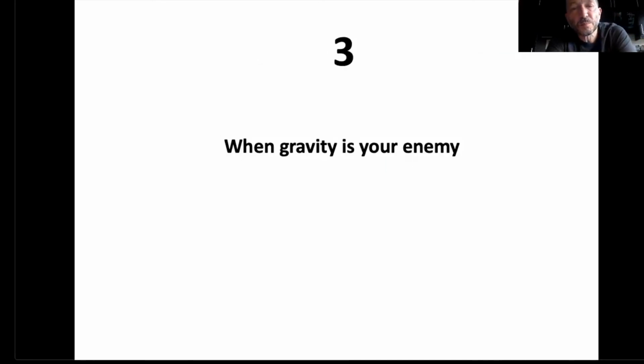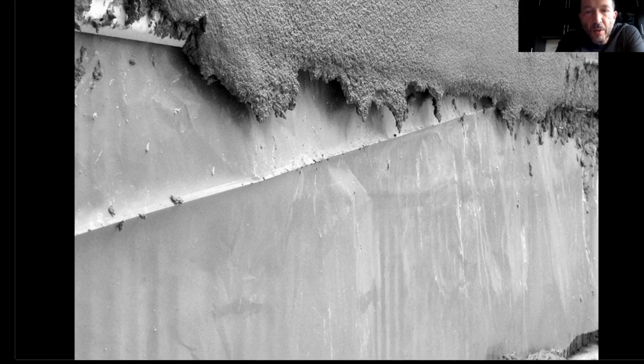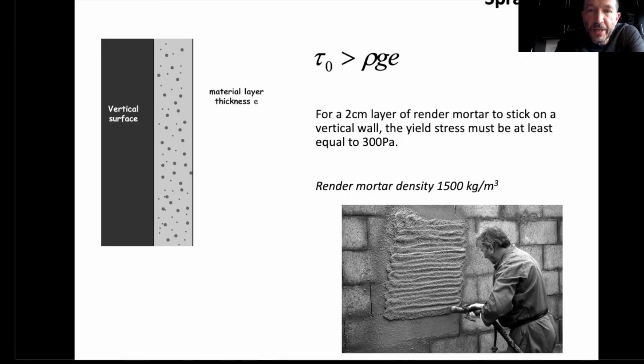The last part deals with the case where gravity is your enemy. The most obvious example is spraying, or rendering. You can apply a mortar, that is what I show here. You can as well apply concrete, internal lining. And in this case, the problem is still using the same relation, except that this time the yield stress must be higher and not lower than the gravity-induced stress. For the material to stick on the wall, for example, this 2 cm layer of render mortar, the yield stress must be at least equal to 300 Pascal.